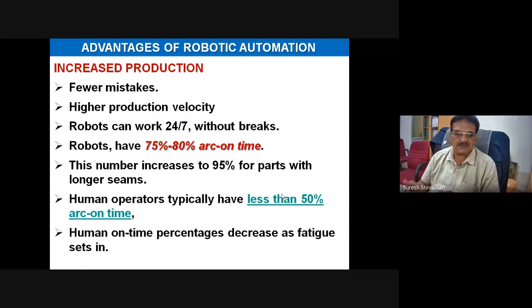So further, with robotic welding, when you build a fully automated system, a robot system which is smart, which has several peripherals to do this handling like torch cleaning, weld cleaning, all those things, it becomes 80%. Now, can I have 100% of arc time in any real life situation? Next to impossible. You can at the best reach 95%, and I have hardly seen any industry crossing this 80%.